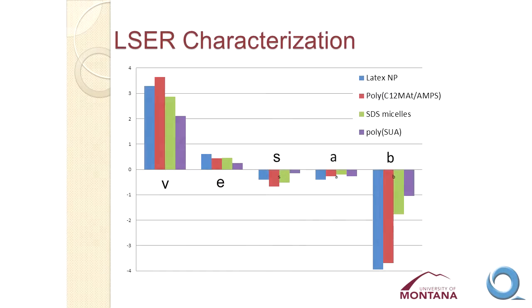We've done this for a lot of different pseudostationary phases. I'm just showing a few results here. This is one of our latex nanoparticles that I'll talk more about in a few minutes. This is a copolymer, a statistical or random copolymer of dodecyl methacrylate and acrylamidomethyl propane sulfonic acid. The green is SDS micelles, and the purple is one of those polymeric surfactants, one of those poly soaps. What we're seeing is that V and B are the most important terms in determining the retention in these systems. V is that dispersivity term, and B is the basicity of the solute.